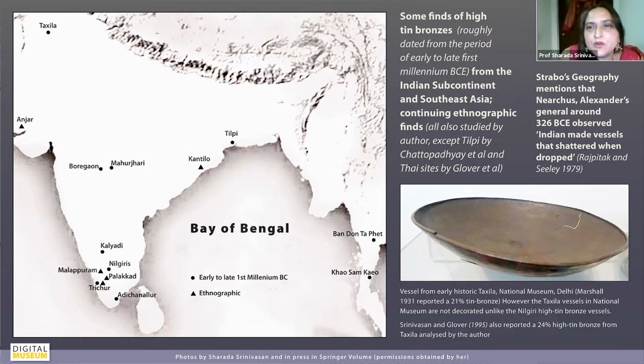This is a map which points to some of these finds of high-tin bronzes, roughly dated from the early to late first millennium BCE, from the Indian subcontinent and Southeast Asia, and continuing ethnographic finds, of course, which I've also pointed to. Many of them have been studied by me, but a few have been studied by other scholars, such as Tilpi by Chattopadhyay. Though, of course, the Tilpi finds are actually more of a 19% tin bronze. It's not really the pure beta phase of 23% tin, but it shows that there is the use of high-tin bronzes in various other places.